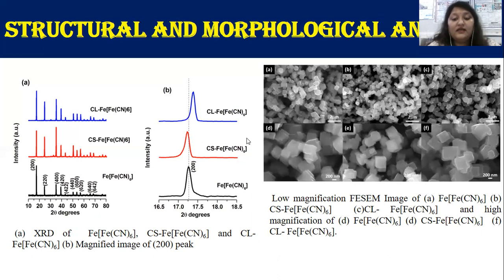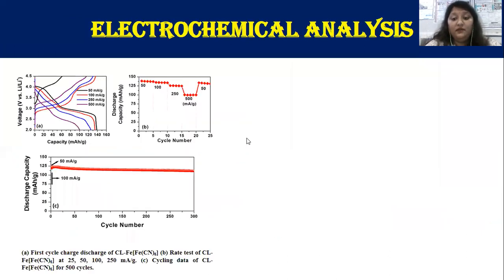in the structural analysis. So the electrochemical properties plot shows the rate study in figure B, and the corresponding charge discharge profile is indicated in A. The initial charge capacity of the sample was only 61 mAh per gram, whereas the discharge capacity reached 138 mAh per gram. And this indicates an incomplete chemical lithiation process.